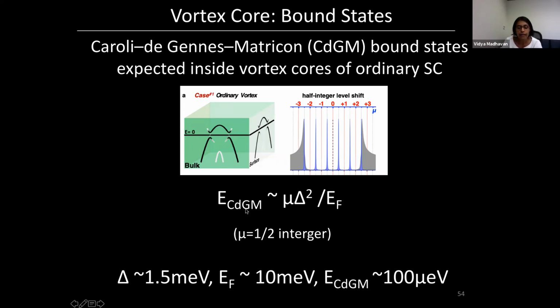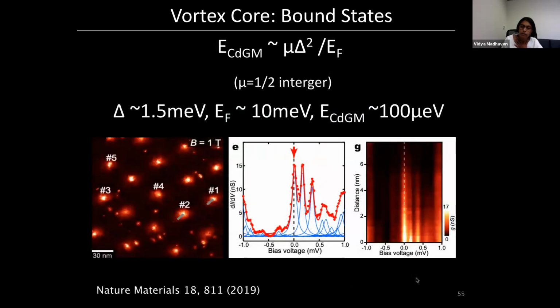You can show that the energy of these vortex core states is proportional to the square of the gap magnitude, which is the distance between the coherence peaks, and it's inversely proportional to the Fermi energy. For our system, you can ask where these ordinary vortex core states should live. In this particular system, if you put down all the values for the gap, the Fermi energy, and so on, you can show that the first one should be 100 millivolts from the, microvolts, sorry, 100 microvolts from the Fermi energy.